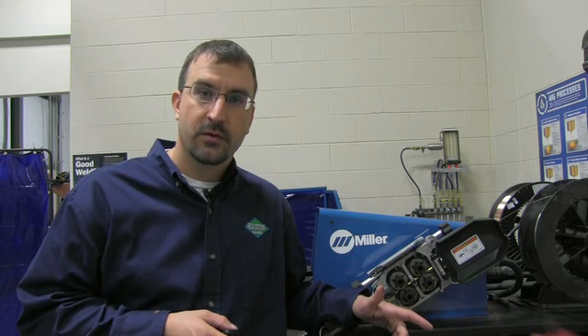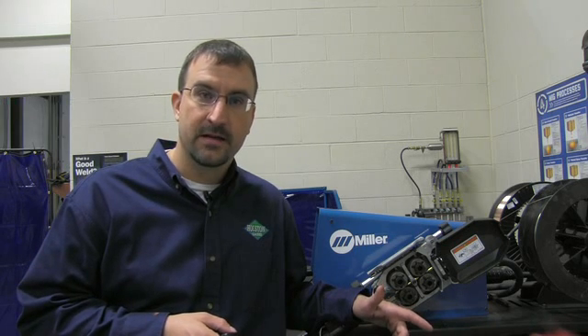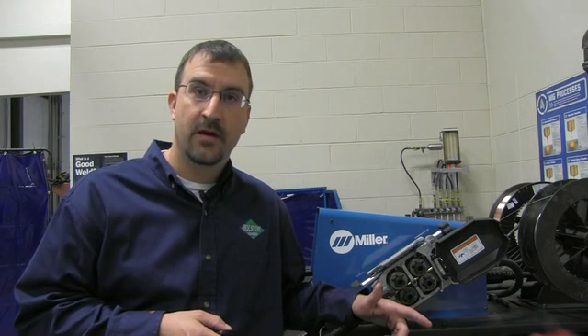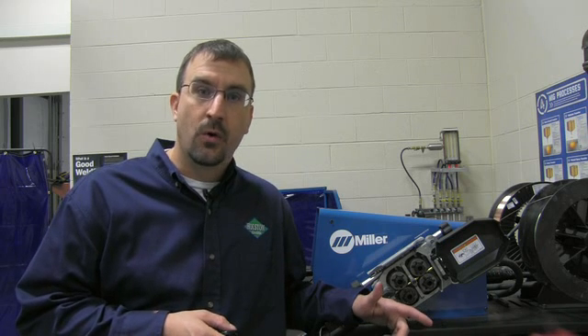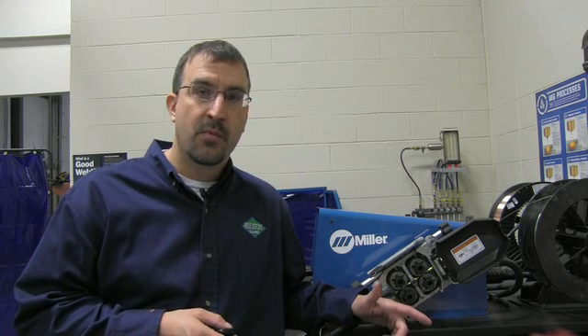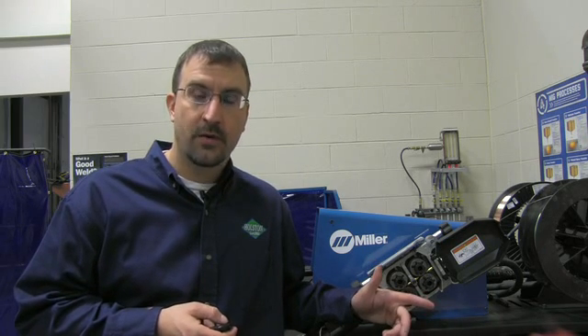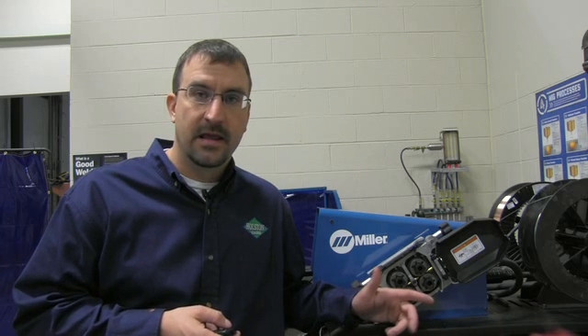So some of the causes of porosity are excessive nozzle to work distance, excessive travel speeds, winds or drafts in the welding area blowing the shielding gas away, holes or leaks in the gas hose, improper flow rates, improper welding parameters, a bad MIG gun, and contamination on the work plate, which is a big cause of porosity. The list just goes on and on. But here I'm going to show you a simple item to check that causes porosity and is often overlooked and leads to extended troubleshooting times.